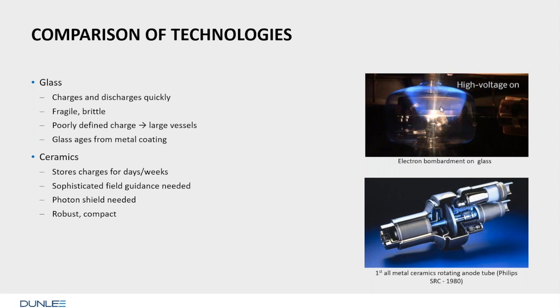So if a glass tube is in heavy ion bombardment and electron bombardment, the glass is subject to currents, and that's not good because the glass is not very stable. It is brittle, it is fragile, and if current flows over glass, it may break and implode. The other thing is that glass charges are poorly defined. They can turn from very positive to very negative, depending on the events. So you need always a surrounding and an environment, the casing, far away to be prepared for all these situations.